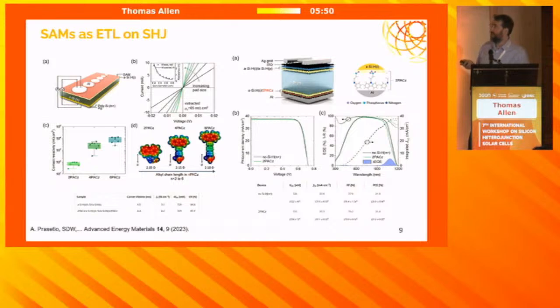And so this SAM is anchored on amorphous silicon that's been oxidized very easily in our box oven that we use for the annealing of our metallization. Okay, and Adi was able to demonstrate with this a very low, for us, contact resistivity, around 65 milliohm centimeters squared, which is significantly better than our nanocrystalline silicon, which is unfortunately significantly worse than state-of-the-art nanocrystalline silicon, but so be it. And with that, he was able to translate that into higher fill factors in control devices. The optics are not very good, so there's a decrease in the infrared response of the cell. But in general, this is a very simple process. You can do it dip-coated, blade-coated, spin-coated, however you want. It's very simple. You dip the SAM solution in, you wash it off, you anneal it, and you're done.